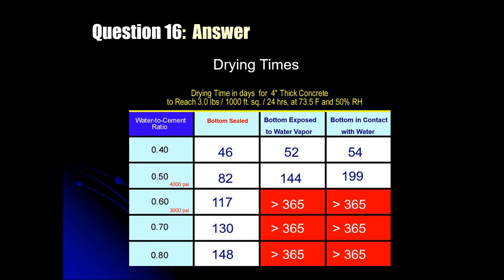Brewer conducted his experiment. It took 82 days for the sealed vessel, the slab, say a slab on an effective vapor retarder on a metal deck, to dry to a 3-pound moisture emission rate. Unfortunately, this kind of study doesn't show a number of things. One, these specimens did not receive a machine-troweled hard steel burnished finish, which basically creates a cap on the concrete that slows down the free release of moisture from the slab.